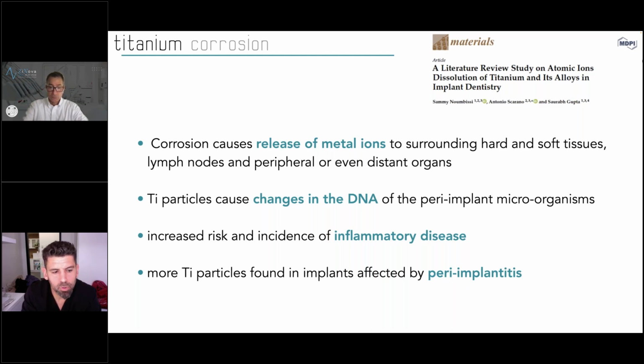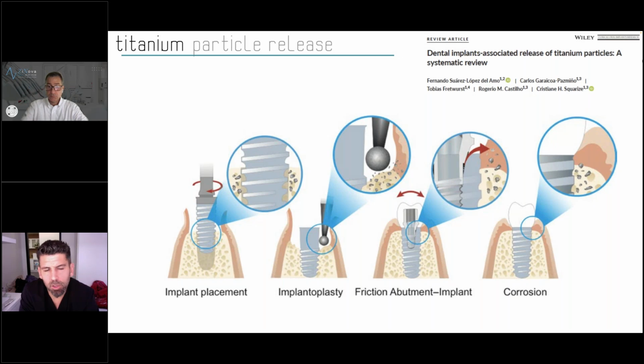And so titanium corrosion and titanium particle release occurs, and that is quite common, and that could be the reason for some of these unexplained peri-implantitis cases that we are seeing. A little bit further, more on titanium particle release.